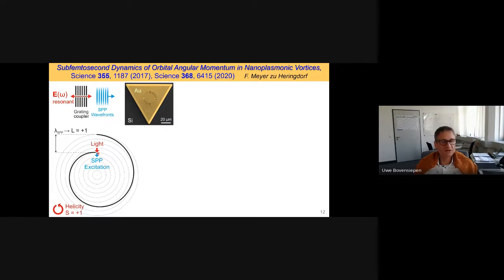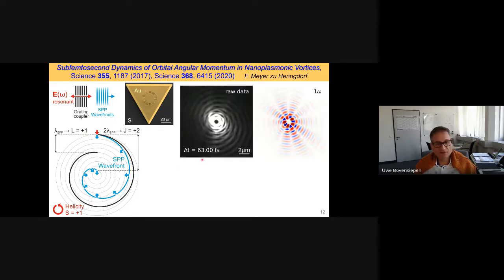This is shown here. So this basically is designed such that upon 2 pi, a resonant condition is fulfilled, that the wavelength of the surface plasmon polariton exactly matches into here. And Frank and his team do this by cutting, with ion milling, these Archimedes spirals into gold nanostructures. And they use circularly polarized light of the indicated helicity. And with very simple considerations, we can now look at how the surface plasmon polariton wavefront propagates. And you see, because of this resonant condition, upon one optical cycle, we have now 2 times the wavelength between the wavefront in the initial and in the final state. So this has increased the angular momentum by +2 simply by mixing the helicity and the orbital momentum of the Archimedes spiral. And this can be investigated in real time using a pump-probe experiment.